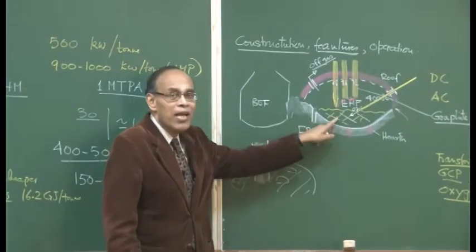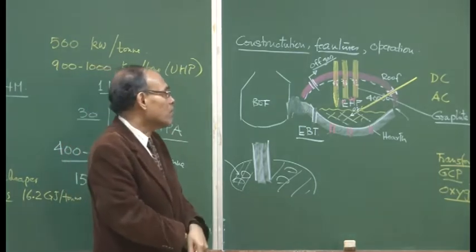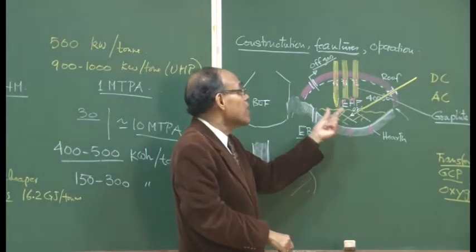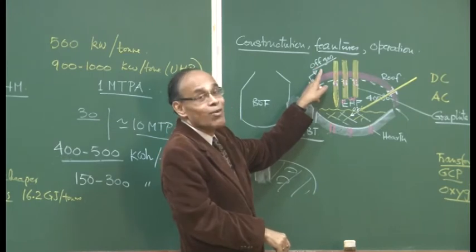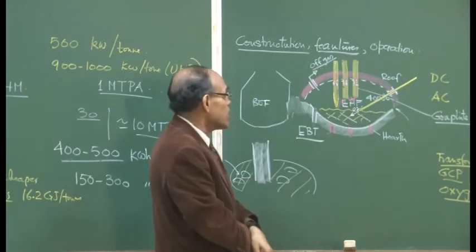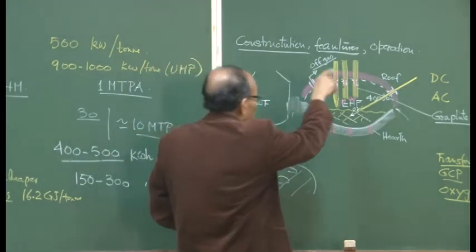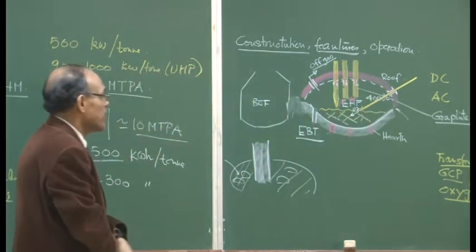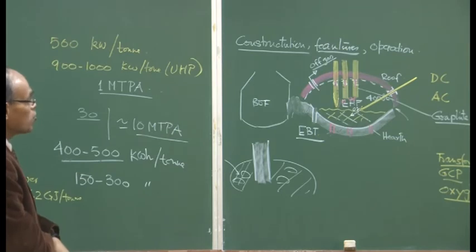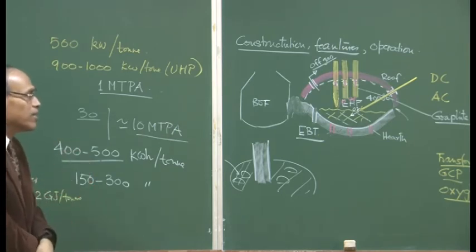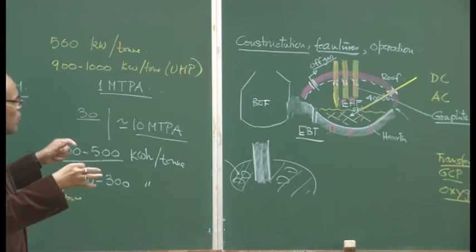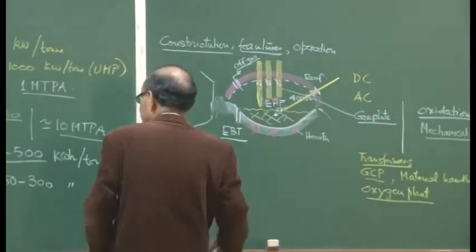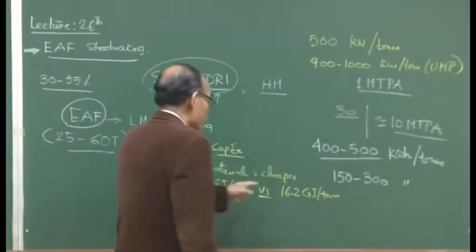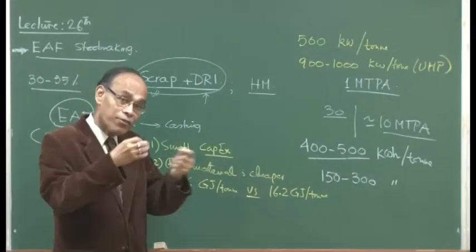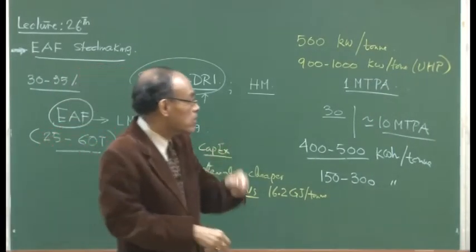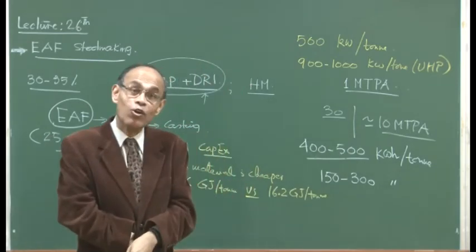And that hot scrap is not becoming hot because of usage of electricity, but it is this heat, the sensible heat content in the off gas, which otherwise will be lost, and that heat you utilize through some arrangement, we will study that. So, analogous to a HYL process of DRI making, there is also an equivalent process here. So, if you can incorporate all these things here, in that case the EAF and the BOF can be, EAF can compete despite a small volume of production of only 1 million ton per annum, it can compete with